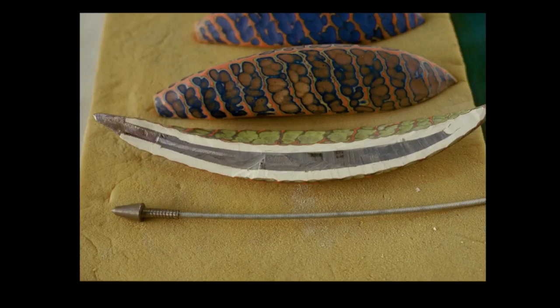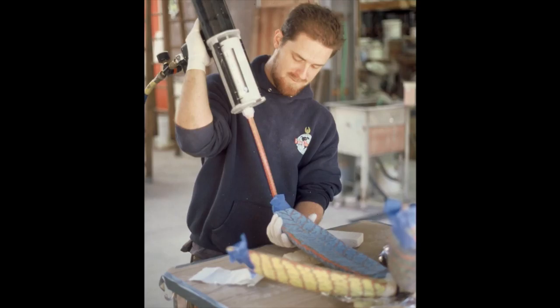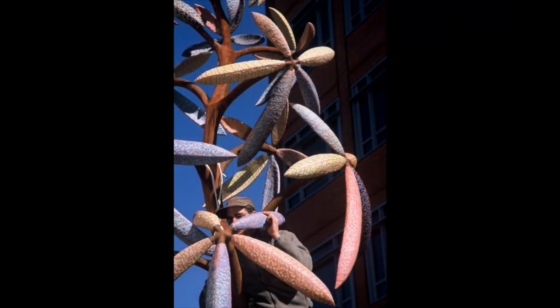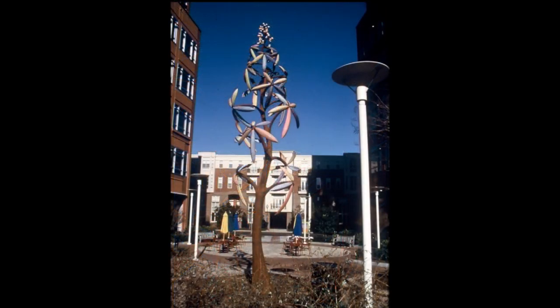My thinking was to use posts that I would join the clay to. On the early small ones, I used urethane to fill them up, and that worked well. But when urethane is chemically combined with what sets it off, it expands. So I was popping the larger objects and having to remake a lot of stuff. I had to rethink my whole procedure. I ended up putting a bird's nest of material around each component, so the buffer was hard clay, a soft urethane cushion between, and the hard steel post. That's the way it stands today.